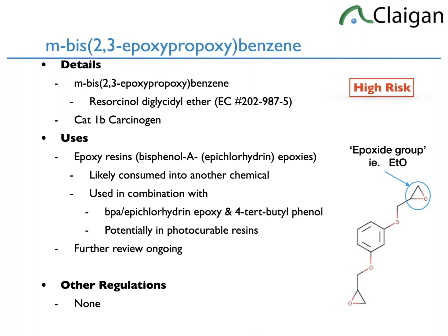The thing is, on a safety data sheet, which these are relatively common in hard epoxies, bisphenol A epichlorohydrin epoxies, it's often like 30% of the weight of the epoxy. That's 300,000 ppm. Now, most of it will be gone when it hardens, but the chance of being over 1,000 ppm in the remaining hard epoxy is pretty decent. Going from 300,000 ppm to 1,000 is a lot. So it's hard to tell for sure, but it definitely can be over 1,000 ppm in the epoxy.